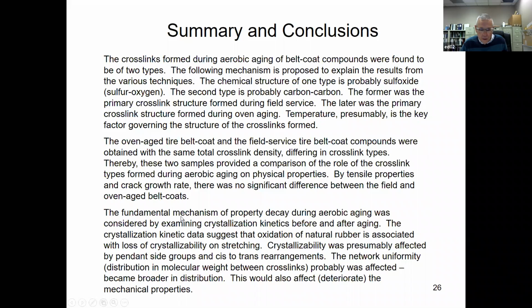The fundamental mechanism of property decay during aerobic aging was considered by examining crystallization kinetics before and after aging. The crystallization kinetic data suggests that oxidation of natural rubber is associated with loss of crystallizability on stretching. Crystallizability was presumably affected by pendant side groups and cis-trans rearrangements. The network uniformity, distribution, and molecular weight between crosslinks probably was affected, became broader in distribution. This would also deteriorate the mechanical properties.